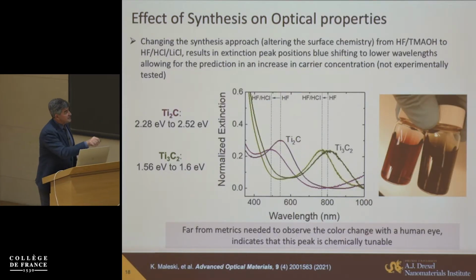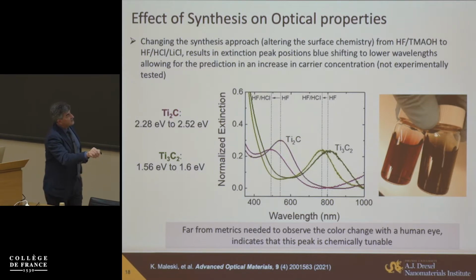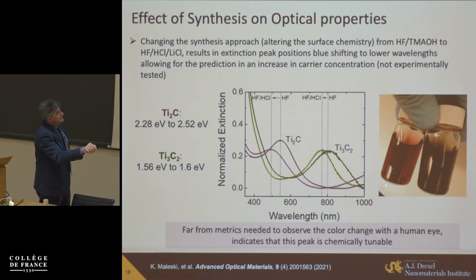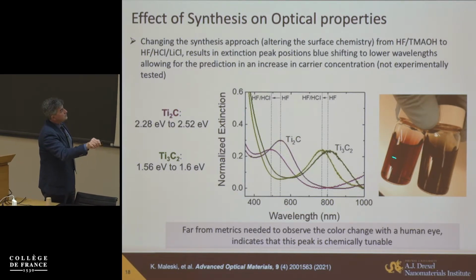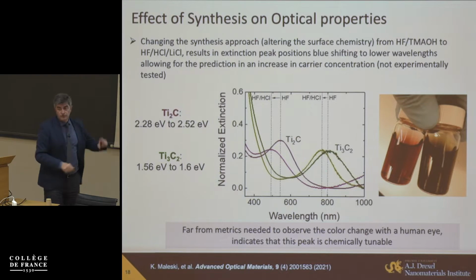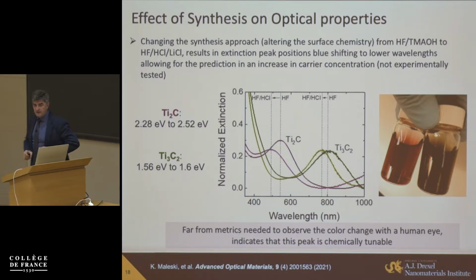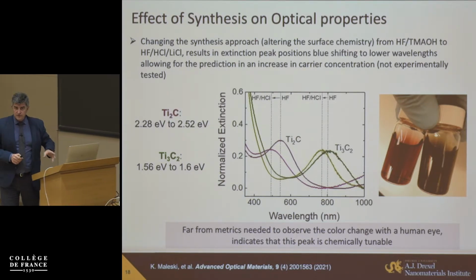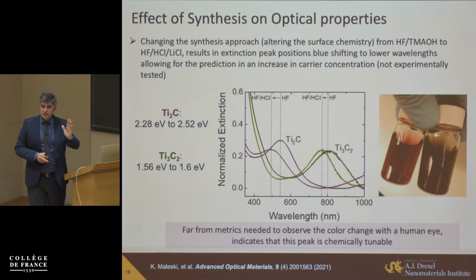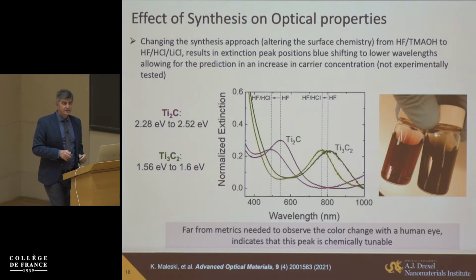And this is an example, I think it's better, you can see colors here, green and red, Ti2C, Ti3C2. Even changes in this surface chemistry will also shift, for example, you remember HF and milder etching, more reduced material. And this is a transverse surface plasmon, and I'll talk a little bit about it further when discussing electrochemistry of these materials here. We can shift its position, really determined just by the oxidation degree of the transition metal on the surface of the material.